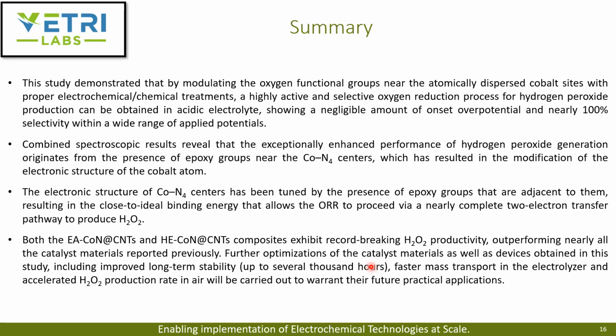So the electronic structure is tuned by the presence of epoxy groups, resulting in close to ideal binding energy that allows the ORR to proceed via the 2-electron transfer pathway to produce peroxide, and not directly reduce it to water, which they observed in the case of iron or nickel. Both the electrochemically activated and the combined composites exhibited record-breaking peroxide productivity, outperforming all the catalyst materials reported previously for peroxide.